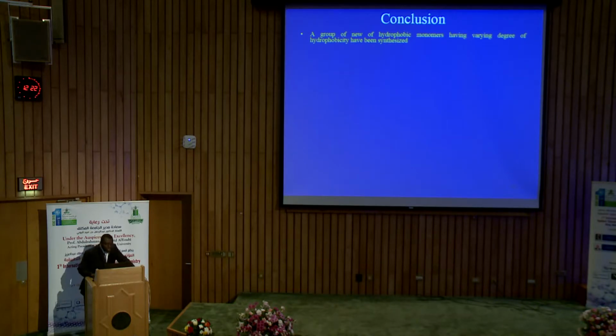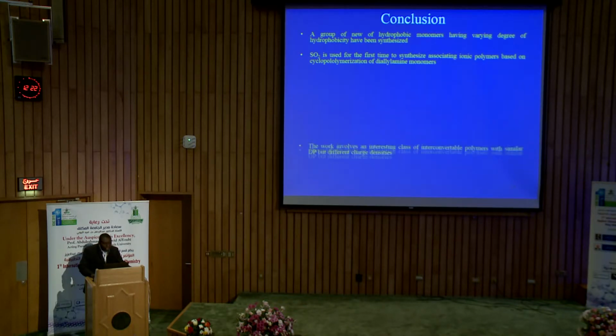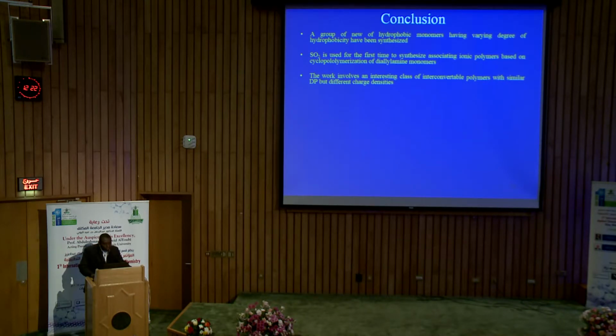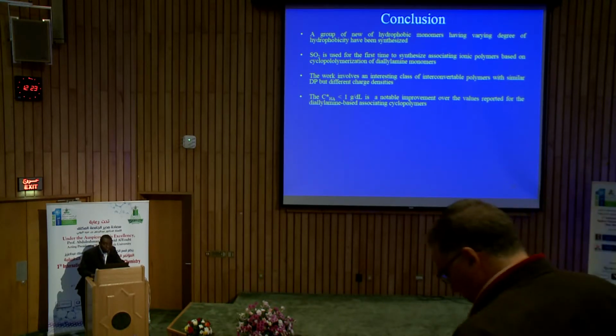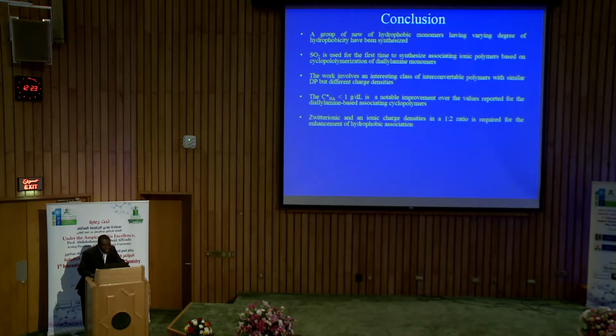And in conclusion, we were able to synthesize hydrophobic monomers with different degrees of hydrophobicity. We have incorporated SO2 into our polymer to increase the solubility. This work involves a lot of interconversion, but we try to make the molecular weight as similar as possible because all the reactions were done at the same time to avoid the effect of initiator or temperature on our polymers. We also have achieved a critical hydrophobic association concentration of less than 1, which is 0.3%. And finally, we can have zwitterions, where we have plus and minus on the hydrophobe just to check the effect of charge density on the polymer.